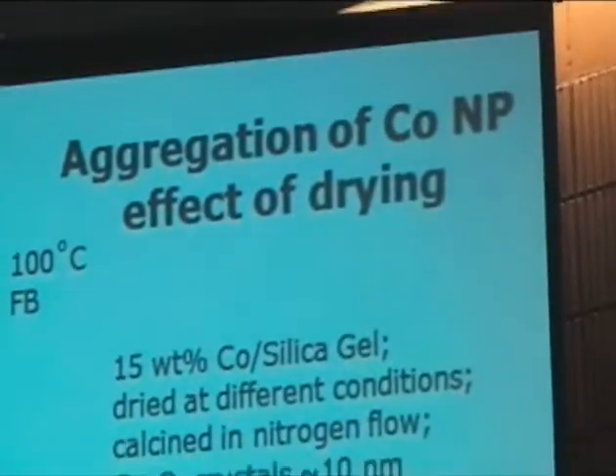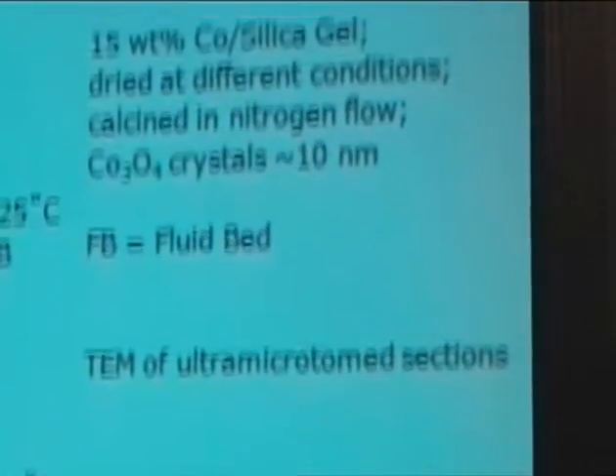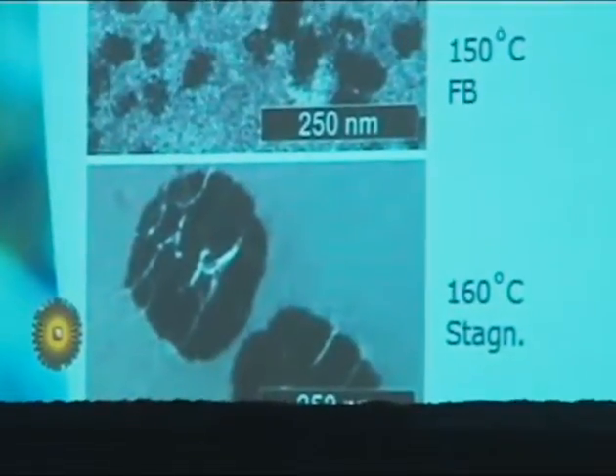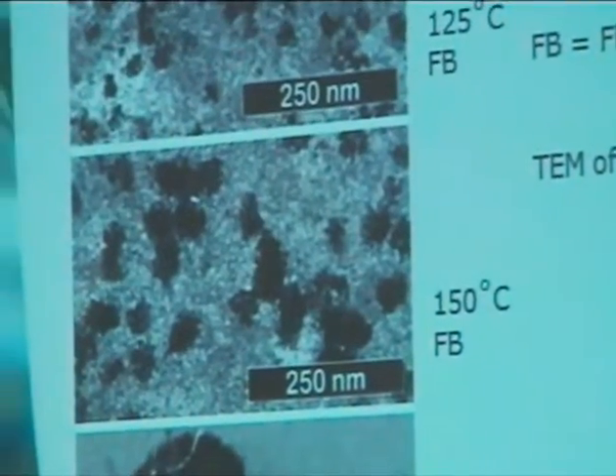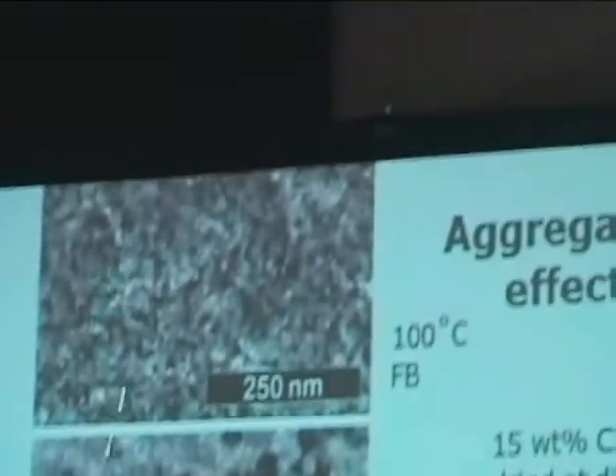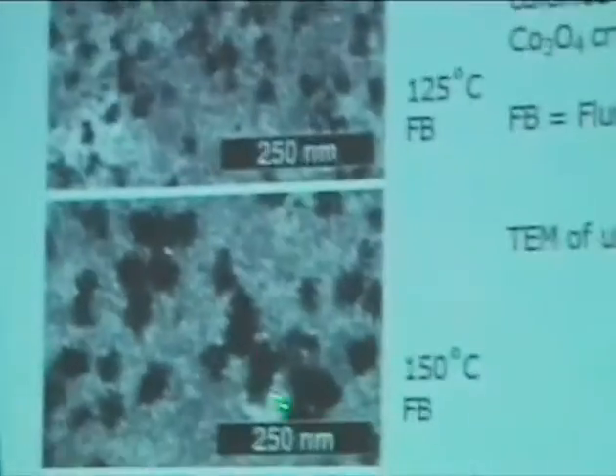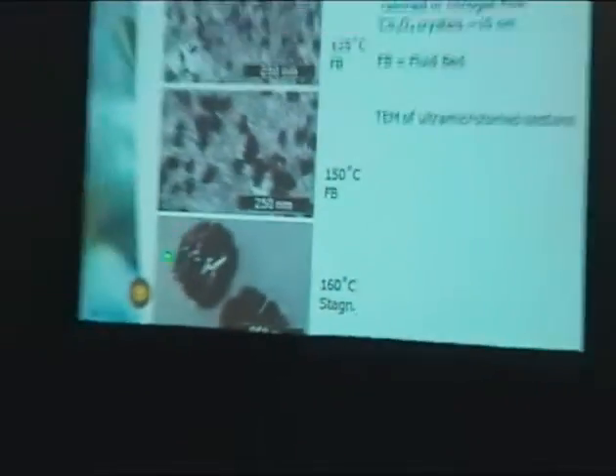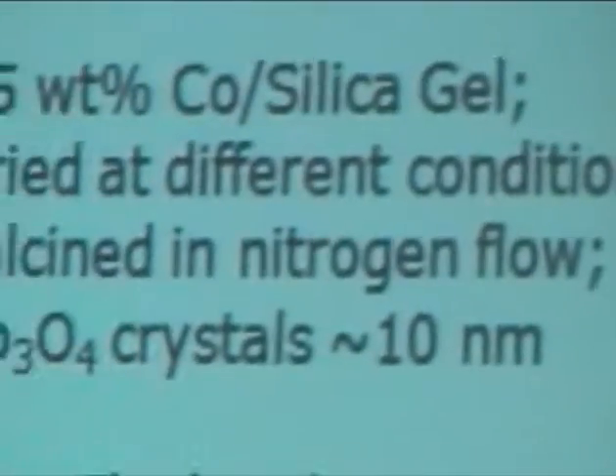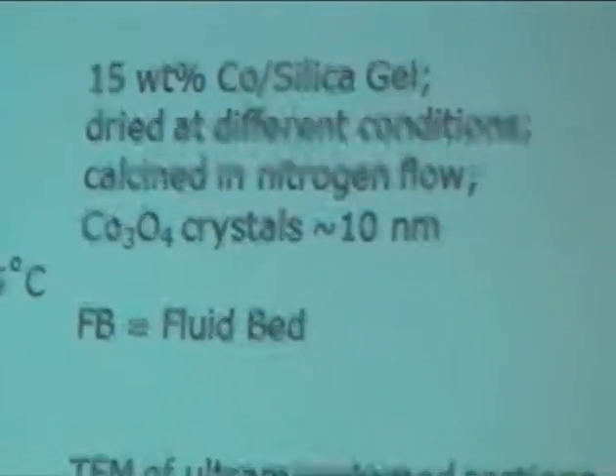Because it's now in a silica gel, we need ultramicrotome sections in order to be able to get good images. And that is what we observe here. We see the different conditions. The scale bar in all cases is 250 nanometers. And this is not a single particle, but rather a cluster of many, many hundreds of nanoparticles. In all cases, the Co3O4 crystallite size is about 10 nanometers. So there's no variation in crystallite size at this stage of the drying and calcination in this case.